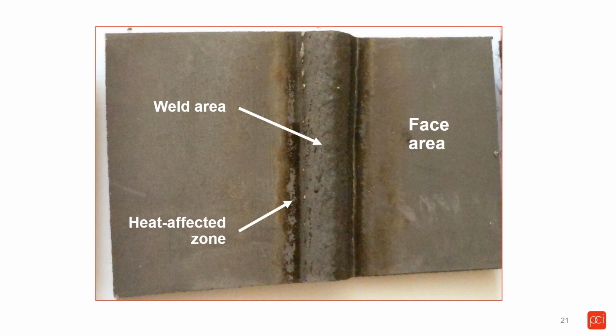The heat affected zone is also an area containing oxides, and sometimes there's weld spatter in there, so you want to try to remove all of that to get a smooth surface. With an acid pickle, you can actually get the heat affected zone to look like a face area, but if you look under the weld area and under a microscope compared to the face area, they're not going to look the same. It doesn't matter how good the acid pickle is, they just won't look the same due to the nature of the welding.